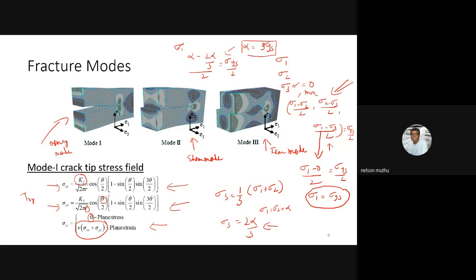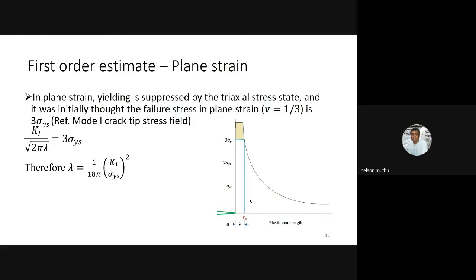So alpha is what? Sigma 1, you can see here. So sigma 1 equal to sigma 2 is equal to alpha. That means you have to reach 3 sigma ys for your material to yield in plane strain, whereas in the case of plane stress, your sigma 1 has to be equal to sigma ys. That is why the size of the plastic zone is reduced. You see here, this lambda is the region where your sigma 1 or sigma yy reaches 3 sigma ys.